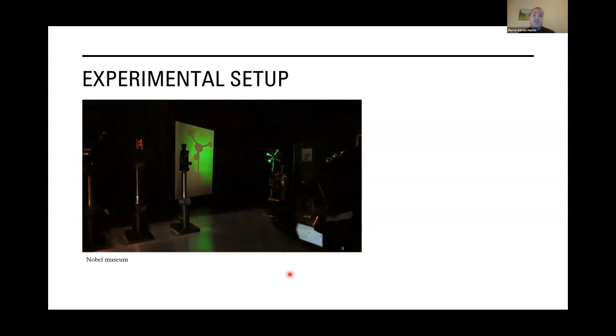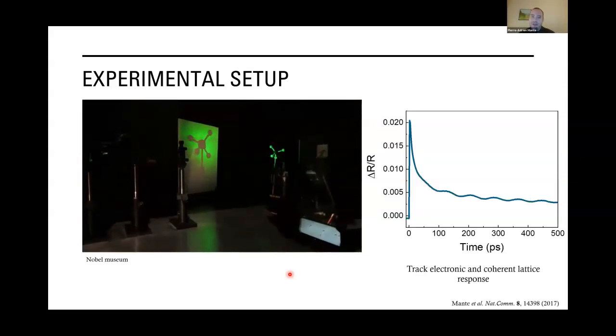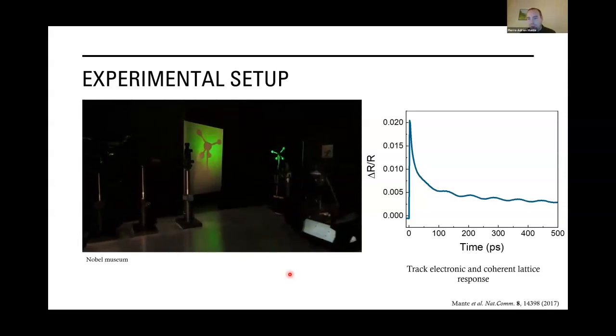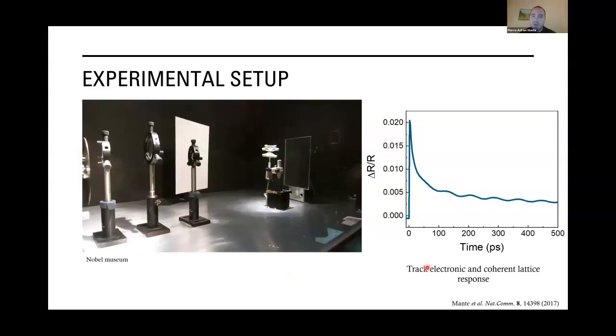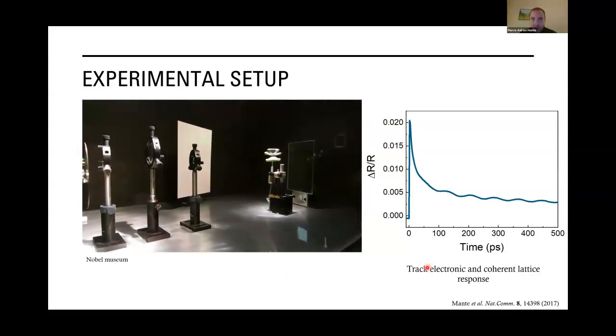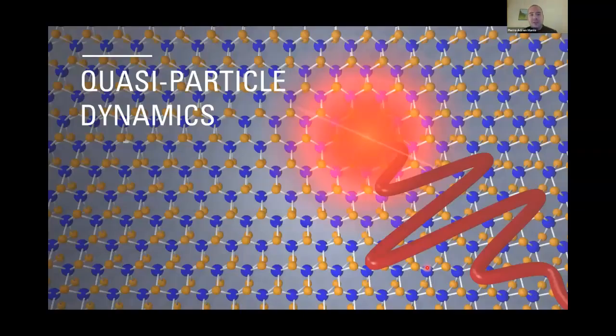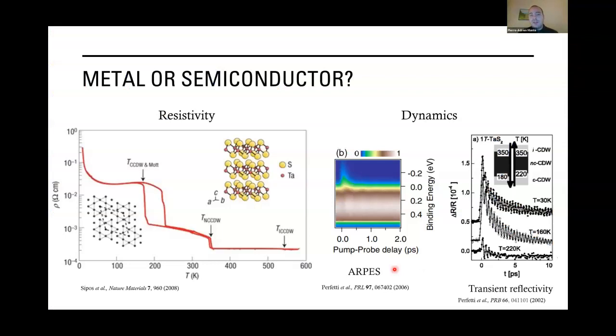With pump probe spectroscopy, we can at the same time track the electronic response and the coherent lattice response. Here is an example in a single crystal of a perovskite material. We wanted to understand the quasi-particle dynamics of tantalum disulfide, and most of all, we wanted to have a coherent, unified picture with the diffraction and photoemission spectroscopy techniques. As I mentioned at the beginning of my talk, the nearly commensurate charge density wave phase has a resistivity that increases when we decrease the temperature. This is typical of a semiconductor material.